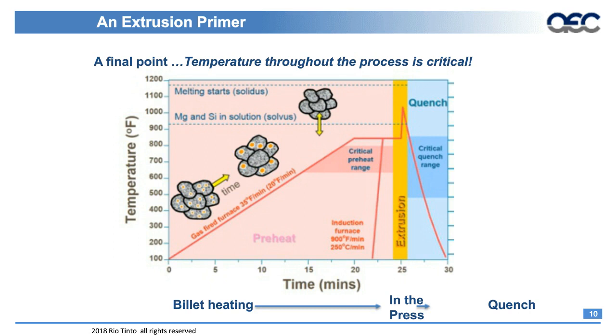And once you hit that quenching operation, you basically cool that material down that's been put into solution, and you solidify that solution into the profile structure of the extrusion. So that's what's happening in the quench phase.